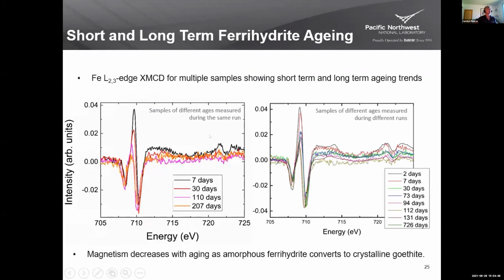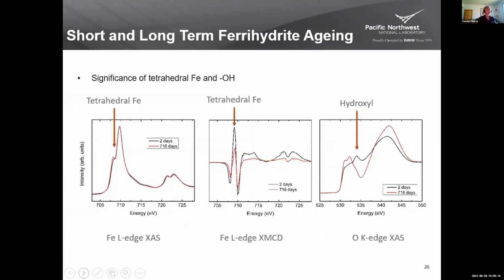And we can look at the magnetic signature of the ferrihydrite, which is a challenge to measure, because we have to measure these at 20 Kelvin, and the signal is very, very weak. So we have to take many, many measurements to actually get these very noisy data. And we showed that the tetrahedral component is present in the very early stages, but it rapidly disappears as you see the structure of the ferrihydrite changing and it converting to goethite.